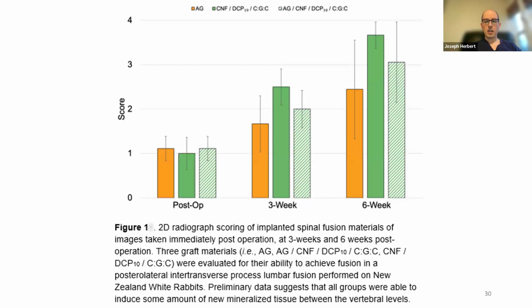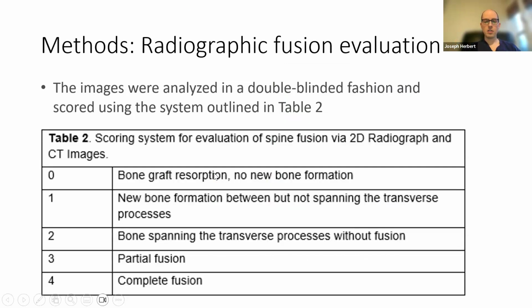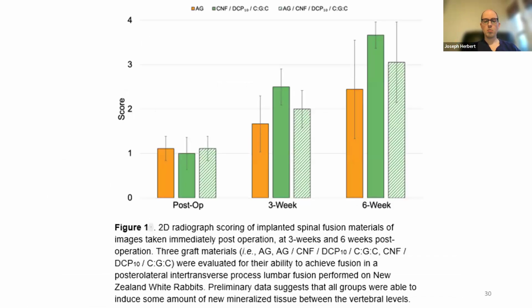So when you look at our results immediately post-op, no surprise, the score is very, very low. Basically, you can see some bone formation. Again, the radiologists were not aware of when these x-rays were taken, of course, as part of the blinding process. Immediately post-op, you could see some material within the transverse processes, but no evidence of fusion. And as you go up to the 3-week and 6-week, the hydrogel itself was actually quite favorable.